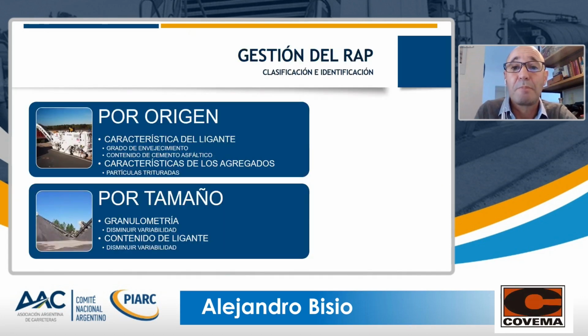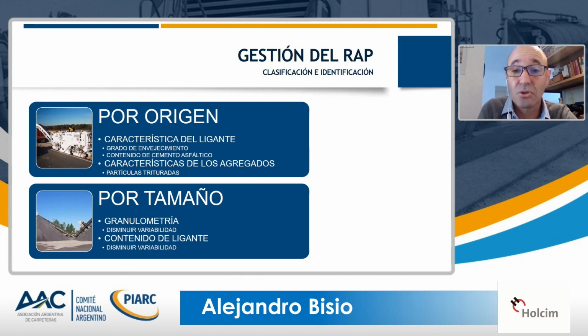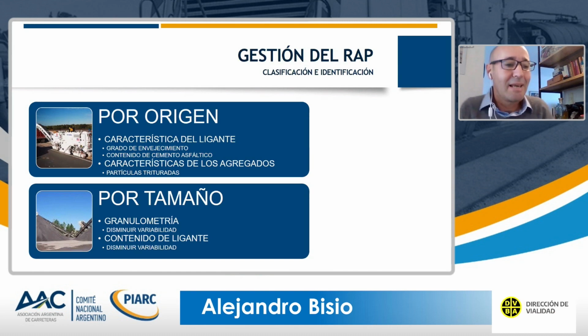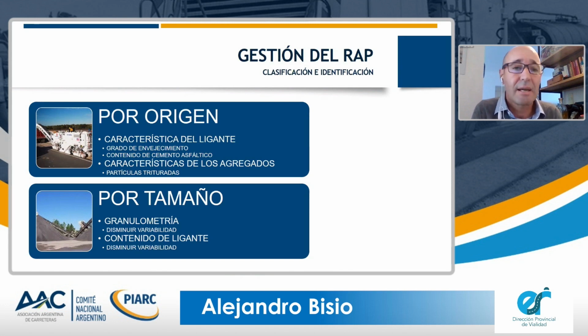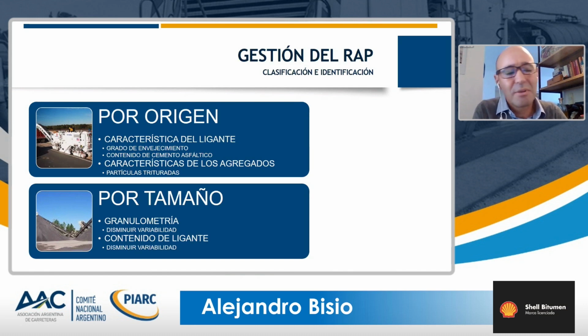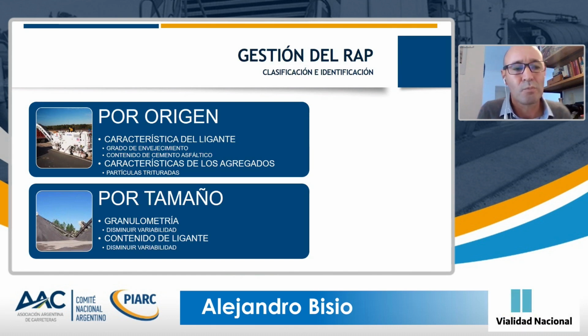Once we had our mixture designed, we went to just making or constructing the mixture. But first, we have a previous stage that is very important in order to be successful in the recycling, which is RAP management. RAP management is all the tasks to reduce the natural variability of the RIP because it's a recycled material. This means that we need to divide RIP by origin or size. We did not do an origin division because everything came from the same place, but only on stretches where patching was done.